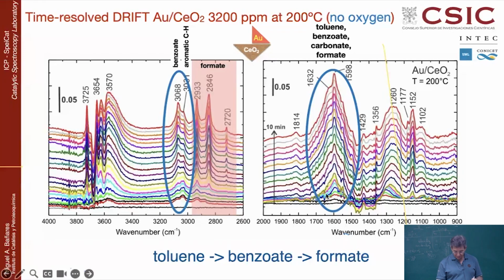Also here, when you are absorbing, you start to see all these bands that correspond to benzoate, carbonate, and formate. These bands look very different than the Raman, because Raman is looking more at polyolefinic carbon deposits, and infrared is more sensitive to oxygen-containing deposits. Which one is true? Both of them, because each technique is looking at what they better measure.